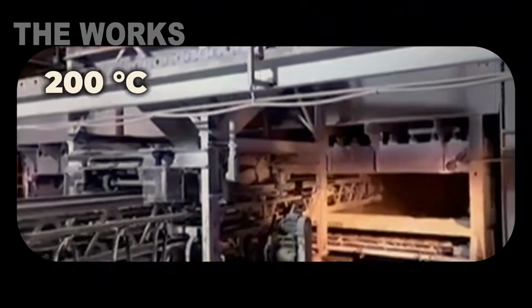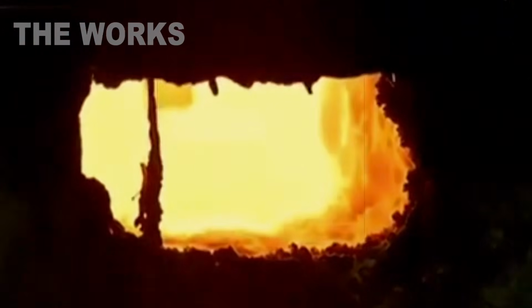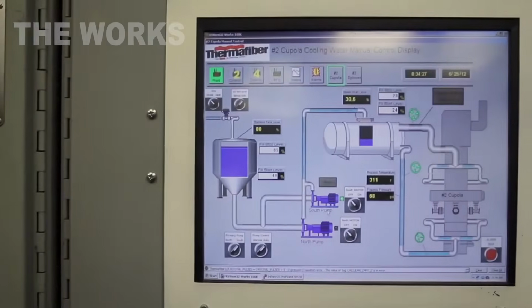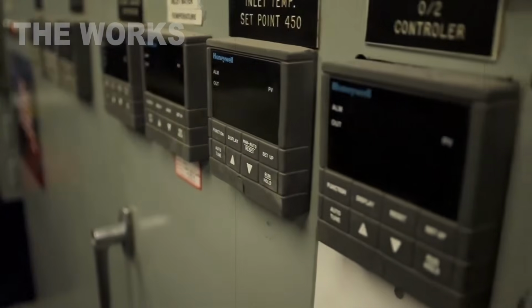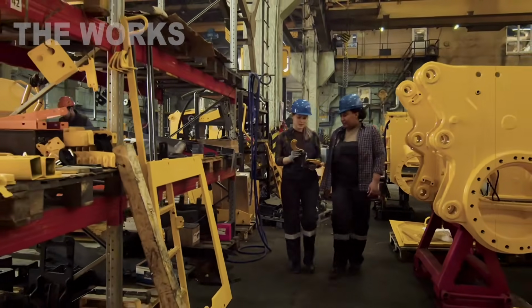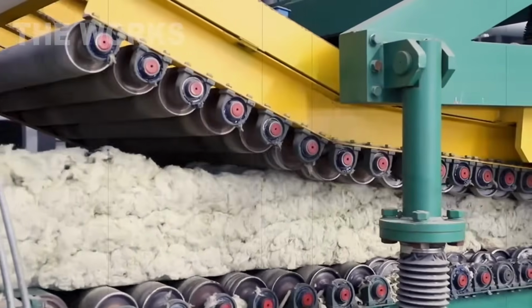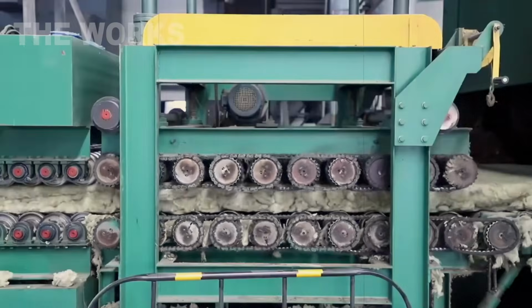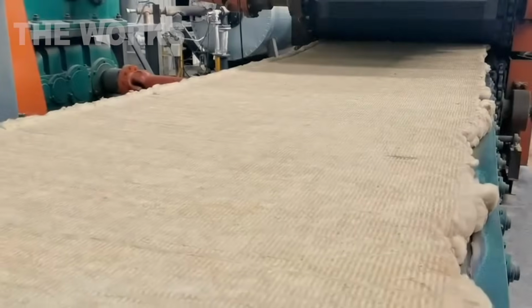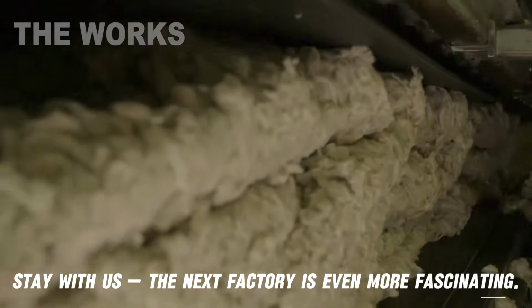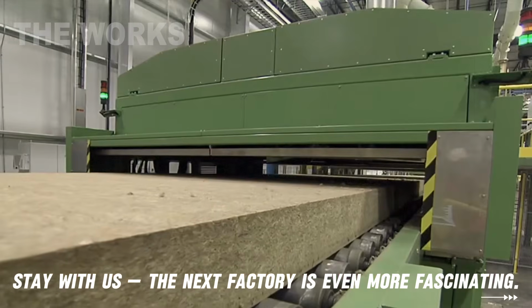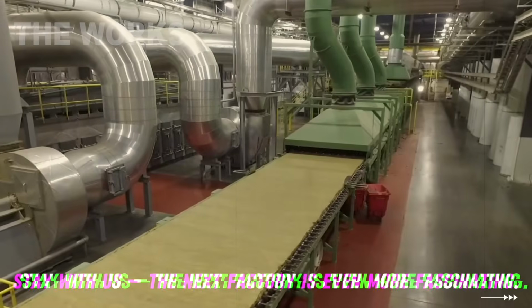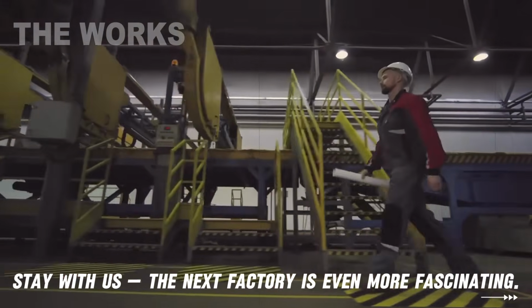The purpose of this stage isn't merely to dry the carpet, but to bake the adhesive. Under heat, the resin polymerizes. That is, its molecules cross-link into a robust three-dimensional network, transforming into solid plastic that permanently bonds the stone fibers at their intersection points. It's within this oven that mineral wool acquires its final properties. It becomes resilient, capable of recovering its shape after compression. During this process, the resin often changes color, lending the finished product its characteristic yellowish-brown hue. From the other end of this gigantic toaster oven emerges no longer a loose carpet, but rather a solid, springy mat of specified thickness and density.